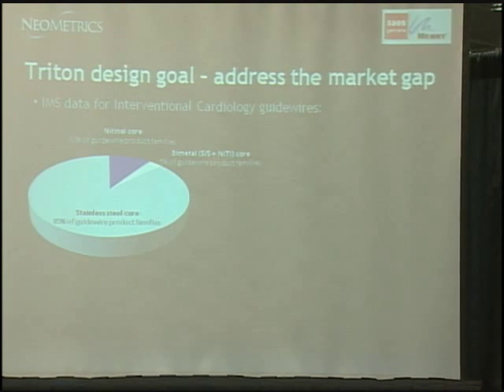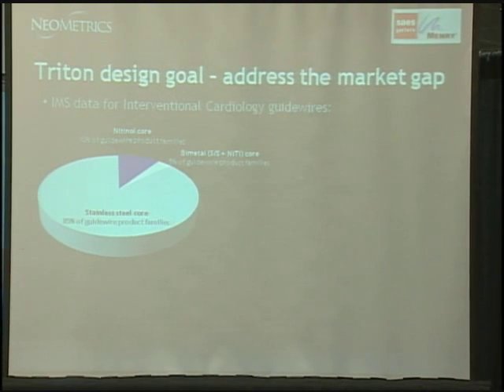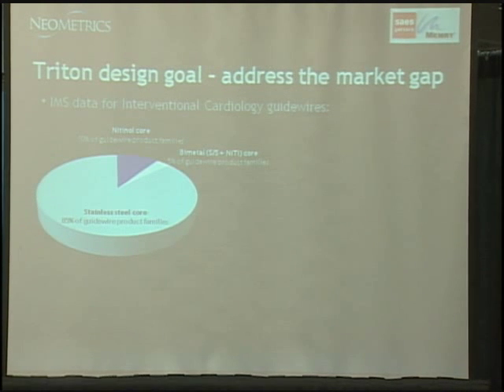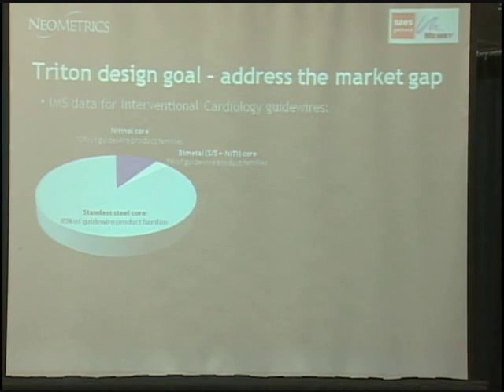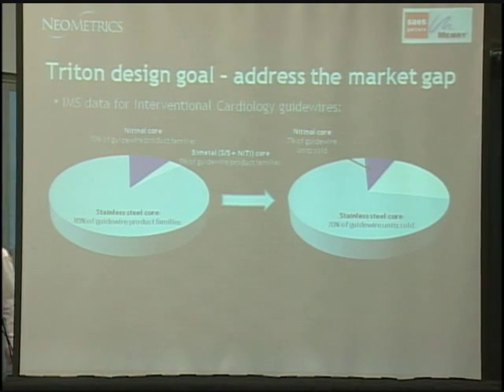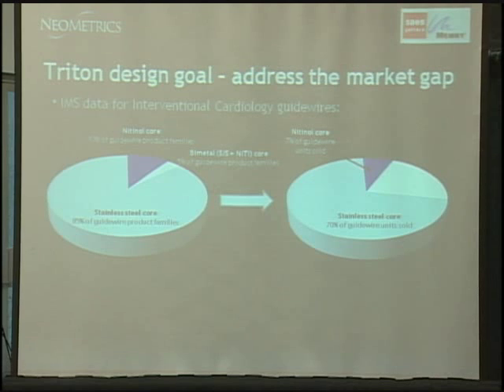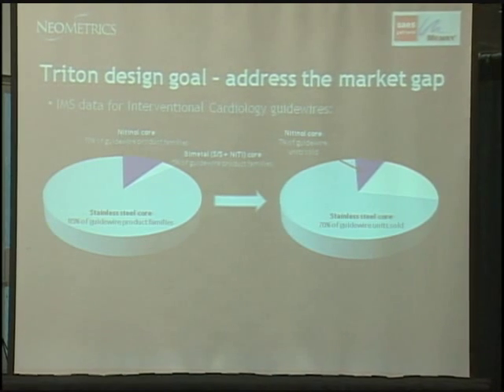So our goal was to really bridge the gap between the stainless market and the nitinol market. And based on the testing that we've done so far, we think this material will actually do that. Right now, in interventional cardiology, only about 10% of the guidewire families that are out there, now these are groupings of products as opposed to every individual code, are nitinol. And the bimetal wires represent about 5% of the families, but they represent a huge percentage of the actual total volume.